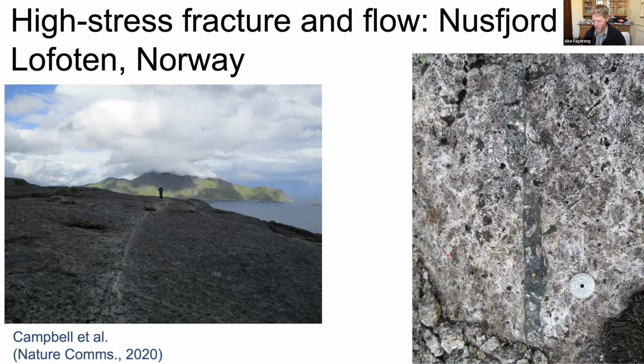But my point here was that at low stresses, getting to even lower stresses with an increased fluid pressure is one way of triggering localization. But what happens if we change that dynamic and say, well, we now have essentially no water, and we're going to localize deformation into pseudotachylites. So, lower crust of Lofoten in Norway: here is a pseudotachylite in dry anorthosite. Here's a zoom in, again pseudotachylite in dry anorthosite, coarse-grained anorthosite, importantly.